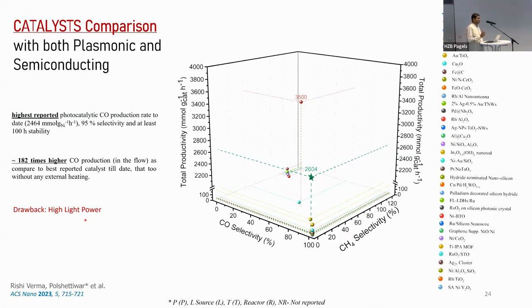And the dream is that you take your reactor outside and do the reaction, right? One sun, 100 milliwatt per centimeter square. What we're using here is 2.7 watt per centimeter square. So that's the challenge still to be resolved. We're trying to design new materials which allow you to do that. Although there is another way of solving this problem, which is more of an engineering problem, where you focus the solar light and get that power. So we're trying to do both things.